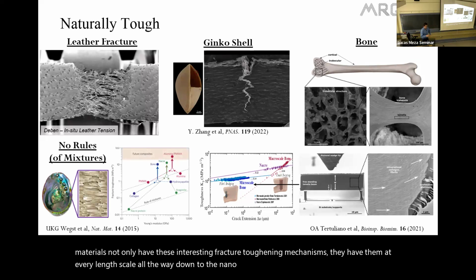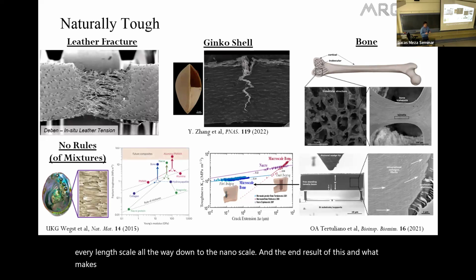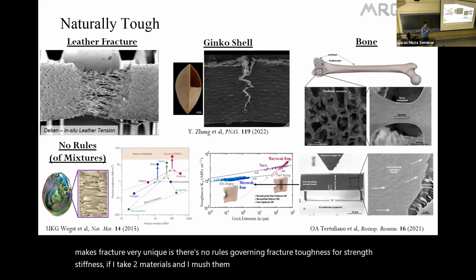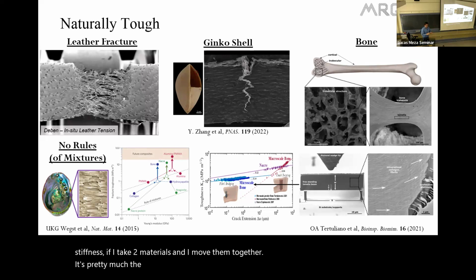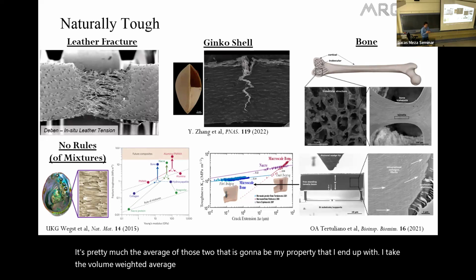And the end result of this, and what makes fracture very unique, is there's no rules governing fracture toughness. For strength, stiffness, if I take two materials and I moosh them together, it's pretty much the average of those two that is going to be my property that I end up with. I take the volume weighted average of the two. I can't exceed a rule of mixtures for stiffness. I can't exceed a rule of mixtures for strength.